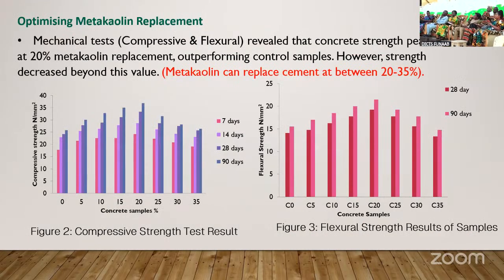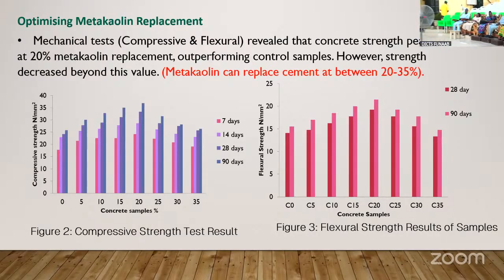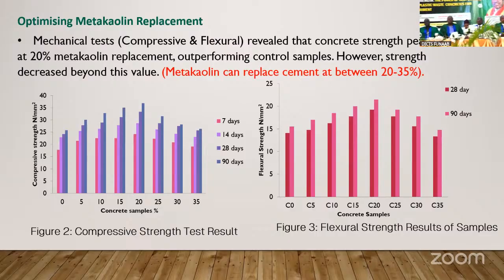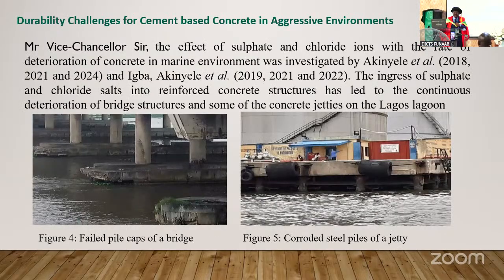The mechanical test. Compressive and flexural tests reveal that concrete strength peaked at 20% metakaolin replacement, outperforming the control samples. However, the strength decreased beyond this value. Metakaolin can replace cement at between 20 and 35%. Durability challenge of cement-based concrete in aggressive environments.